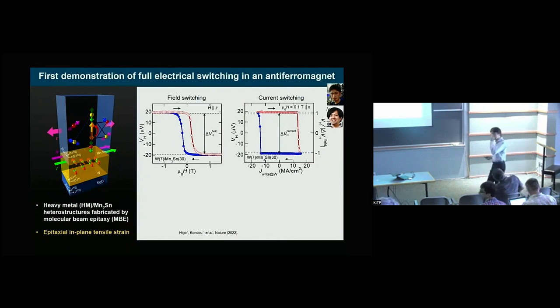Thank you for the talk. My question is kind of selfish, because we did some research on the rare earth analogs of this structure, P63/mmc, and in those cases we never get this inverse antiferromagnetic 120-degree order. So I want to know, why is this inverse 120-degree order stable? And if it's Dzyaloshinskii-Moriya interactions, why should they be strong in this type of structure?